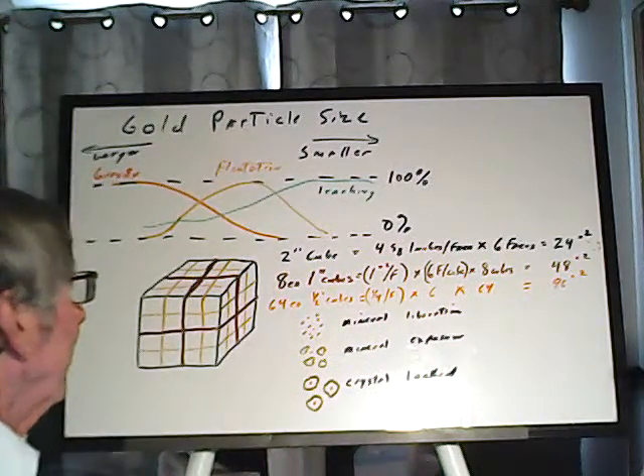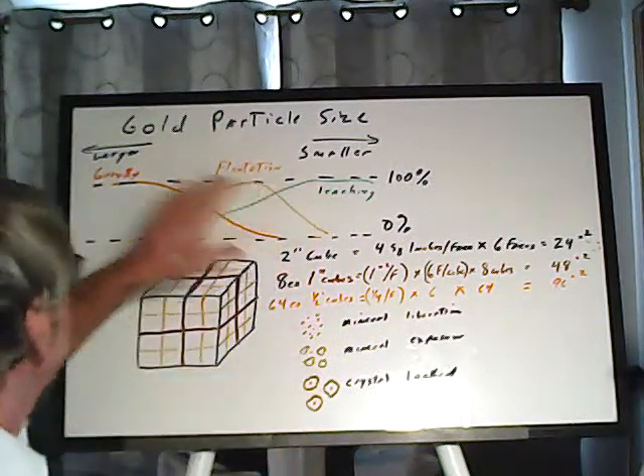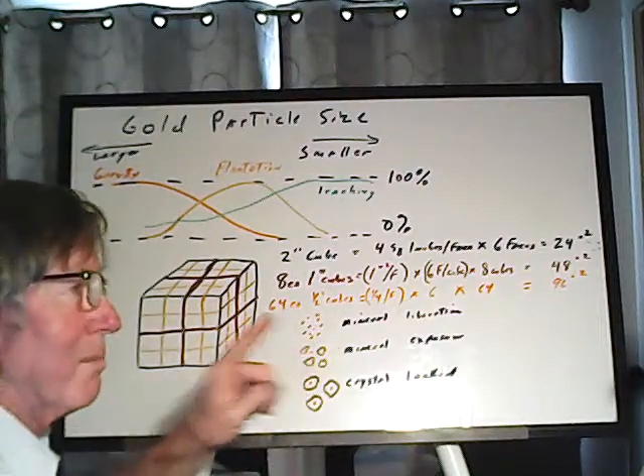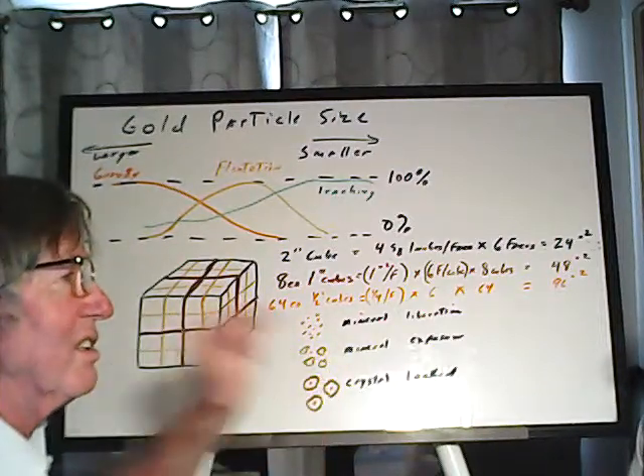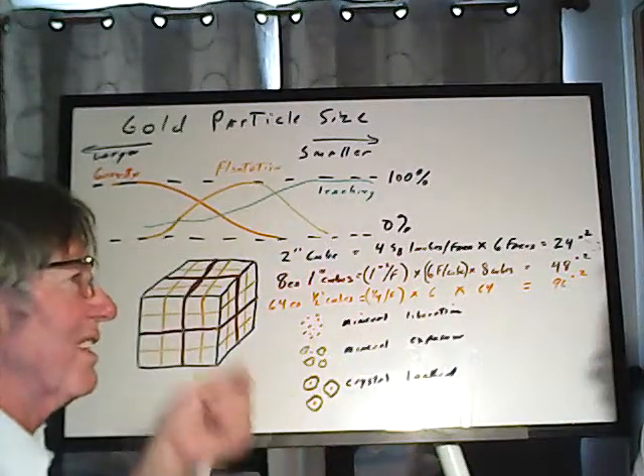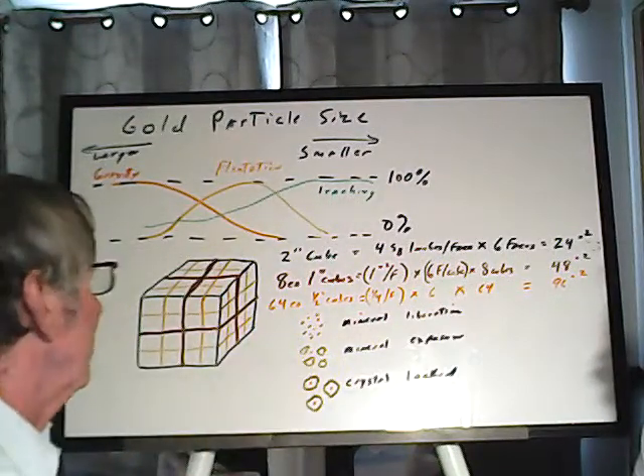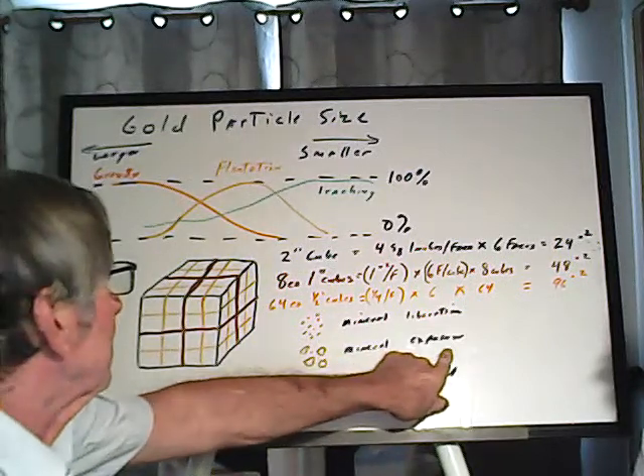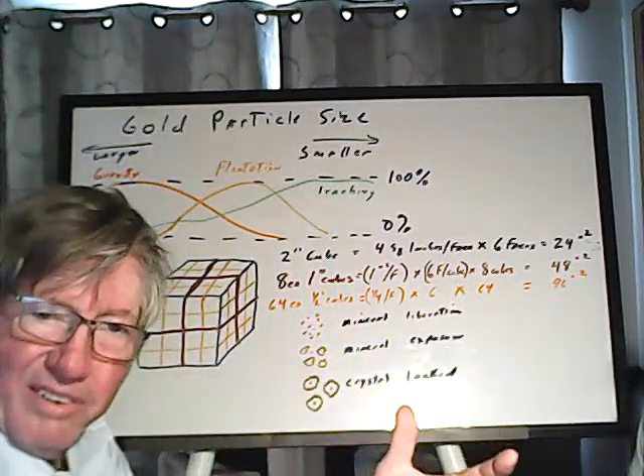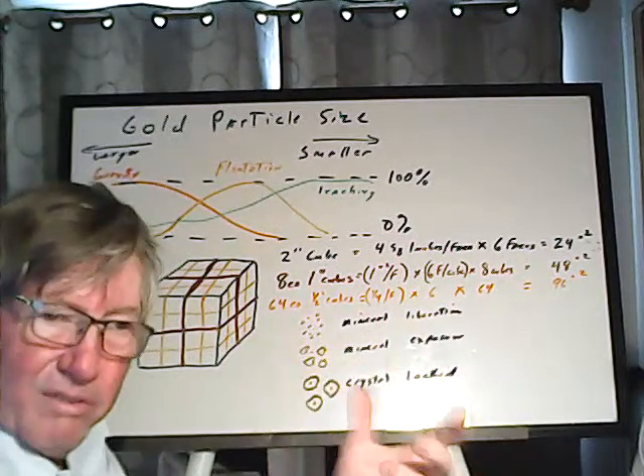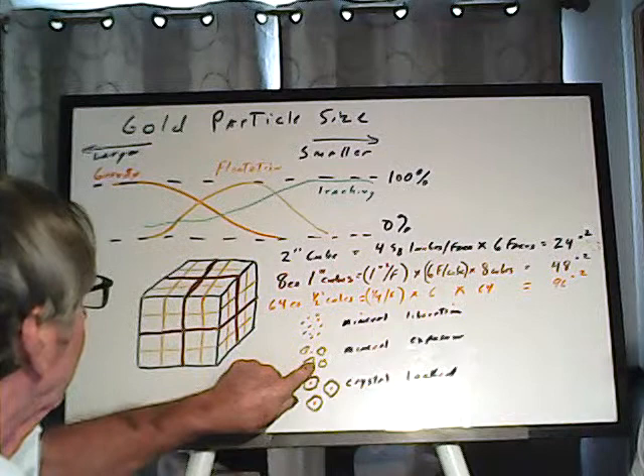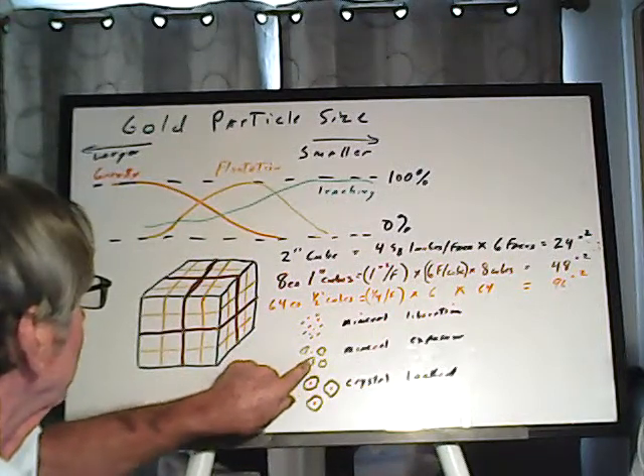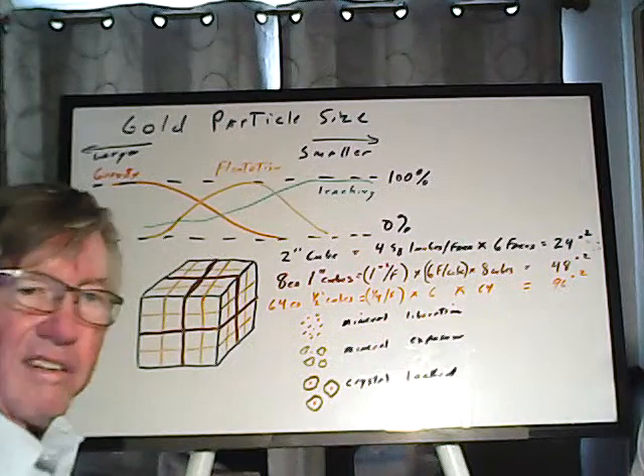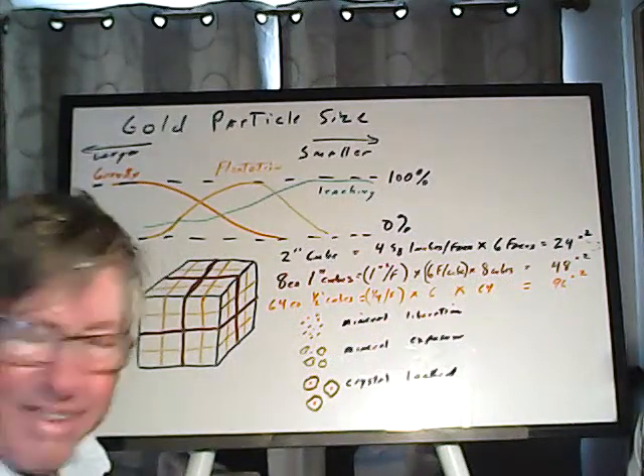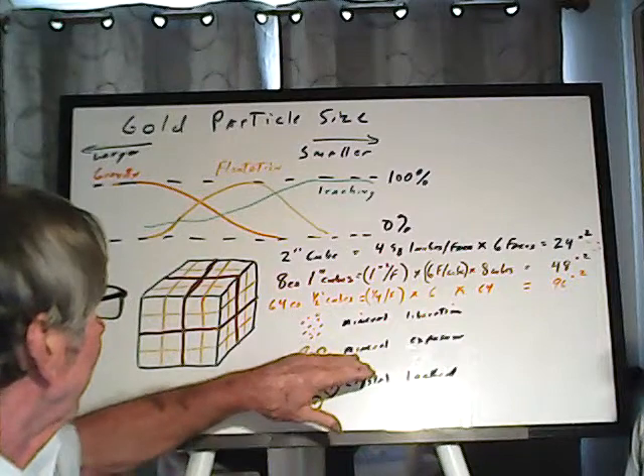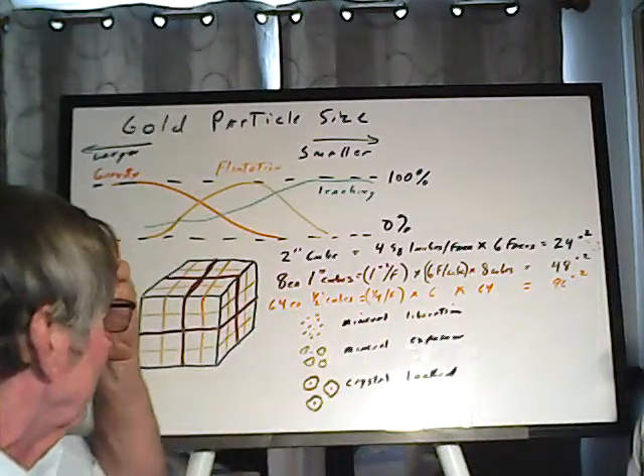It works fine. However, for leaching, unlike flotation or gravity, you do not need to break the gold away from the mineral. You just need to get one side of the gold exposed to the leach solution. That is called mineral exposure. You're exposing the mineral. And that works for leaching. You can go with a larger grind size because as long as those particles are where the leaching solution can get to them, that is adequate. That's not as fine as you need for mineral liberation.